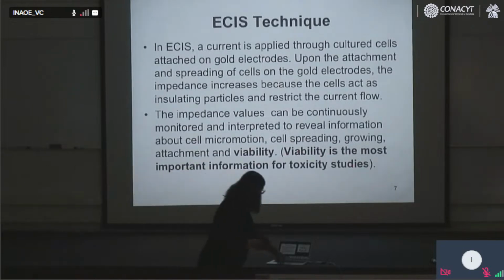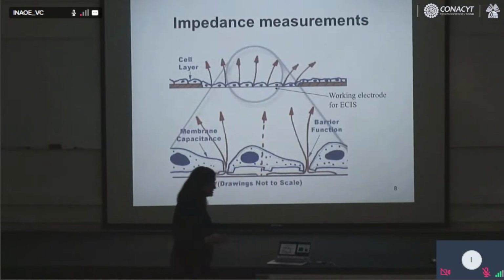And I have here a sketch. I think this sketch is very good to understand the technique of impedance spectroscopy. You have two electrodes, and you apply a pulse between the electrodes. You create an electric field, and the electric field will go through the cell junctions, which are very, very small, at nanometer scale. So the cells are a little bit blocking the flow of the current.